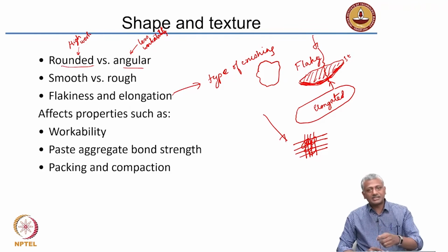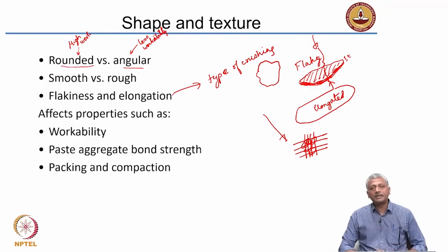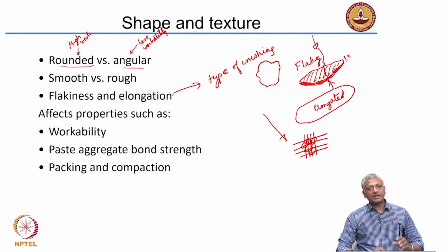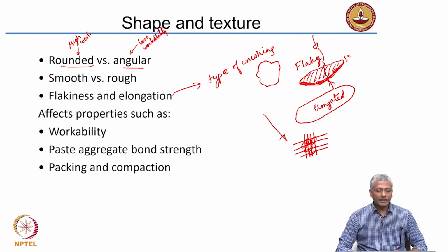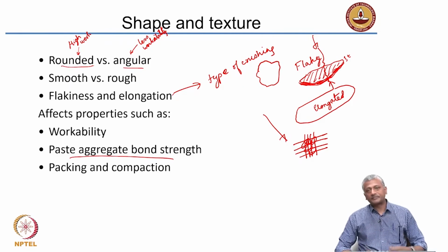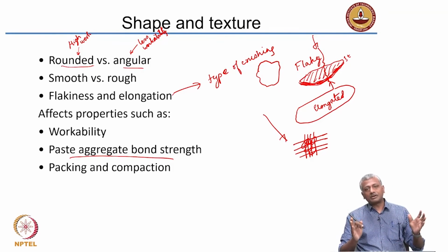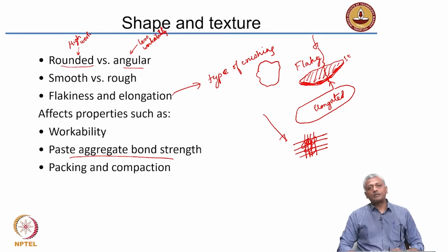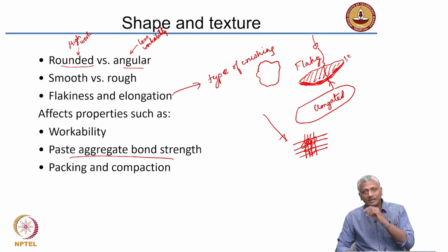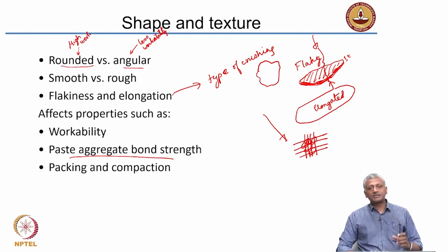So, we typically measure it, as you will see later, in terms of some methods that determine the fluidity or consistency of the concrete. So, when you have rounded aggregates, you get better workability. When angular aggregates are used, you get lower workability. The other aspect is the paste aggregate bond strength. I will talk about this in a little bit more detail somewhat later. Essentially, the strength of the concrete is truly only governed by the paste aggregate bond strength. For normal aggregate, when you start using artificial lightweight aggregate, for instance, the aggregate strength also can be a determining factor. But in most normal concrete, the aggregate or the rock is usually much stronger than the cement paste. As a result of which, the bond between paste and aggregate really affects the strength of the material.